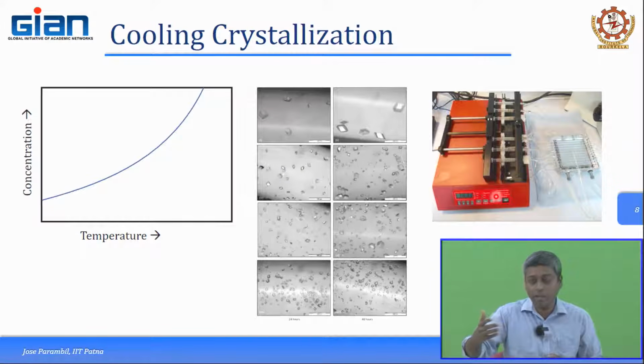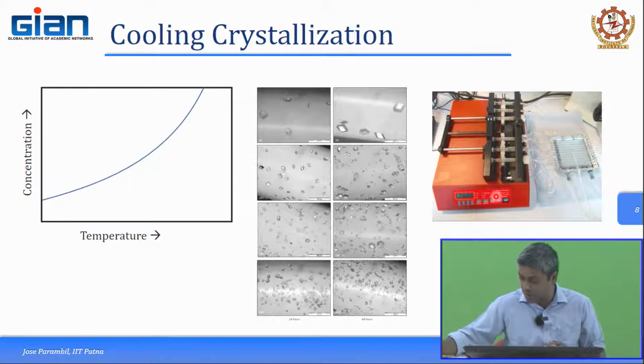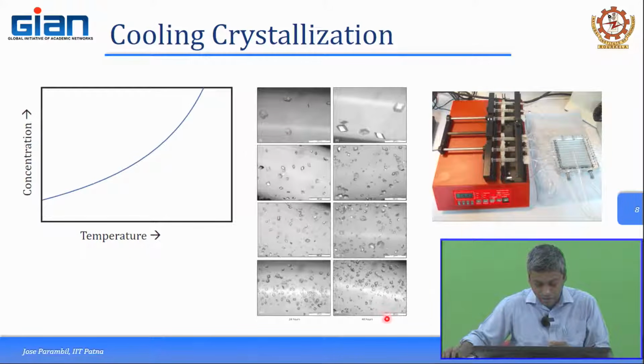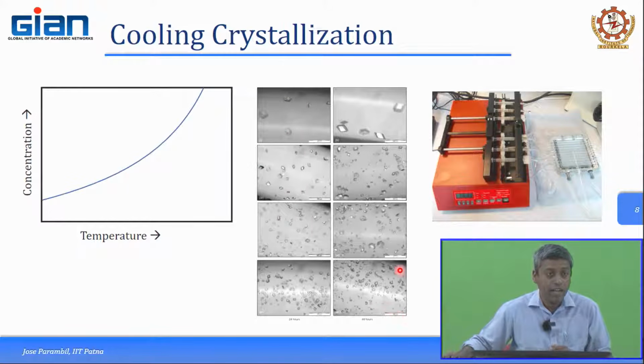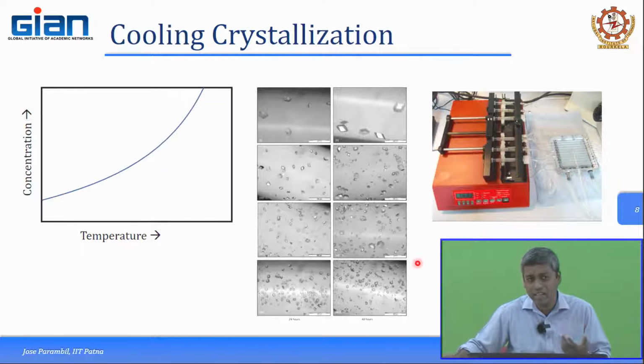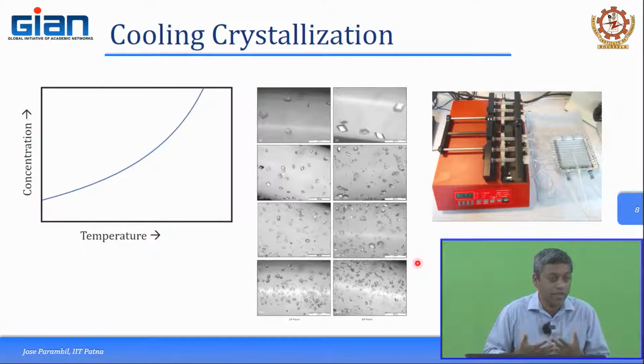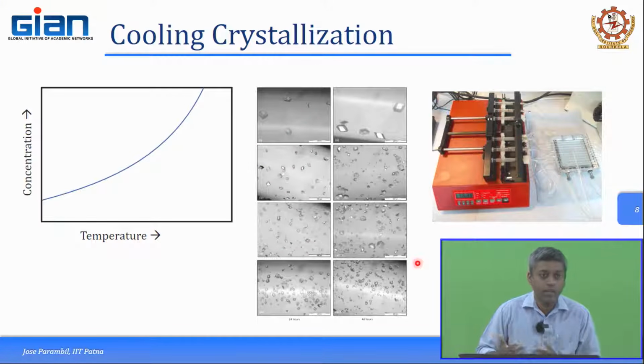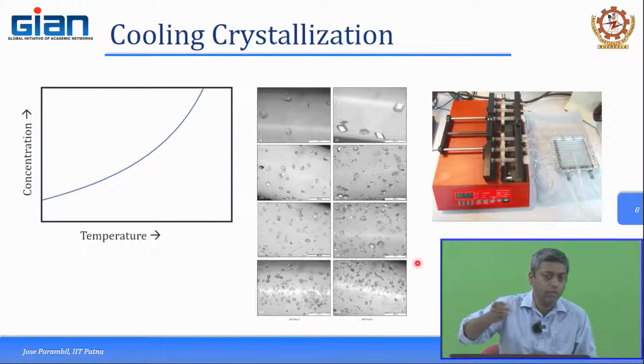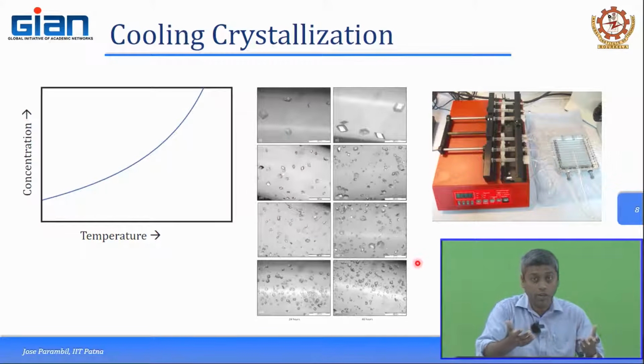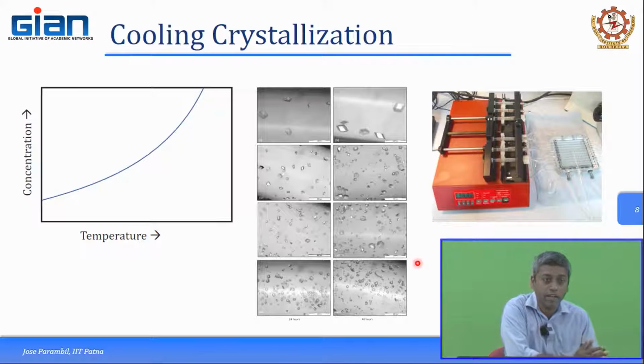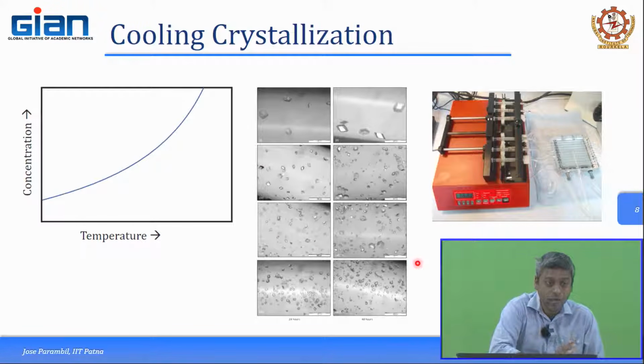Now, at this point of time, the image is not very clean here, but this is about 100 micrometers, and these are very fine crystals which are quite stable as well. During filtration, as long as you do not give too much mechanical force, they do not break, or denature. If you want, you could add a little bit of buffer to wash those crystals, and then if you want to dry it further, you can put it in a vacuum chamber and dry it, and then you get very pure crystals. So, that is one of the easiest ways on a small scale.